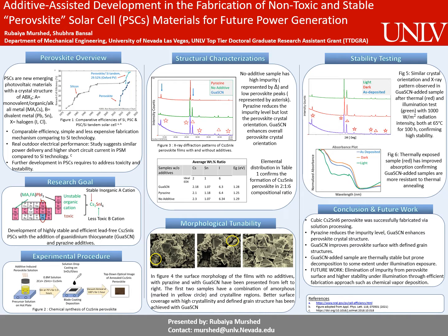illumination. As a summary, we have successfully fabricated dicesium tin hexaiodide perovskite through solution processing, and guanidinium thiocyanate enhanced the overall photovoltaic properties and the thermal stability of the films. There are two main challenges that need to be addressed in our future work. Firstly, complete elimination of the impurity peaks from the perovskite crystal structure, and secondly, enhance the stability of the films under light condition. A more efficient fabrication mechanism can help us solve these issues.